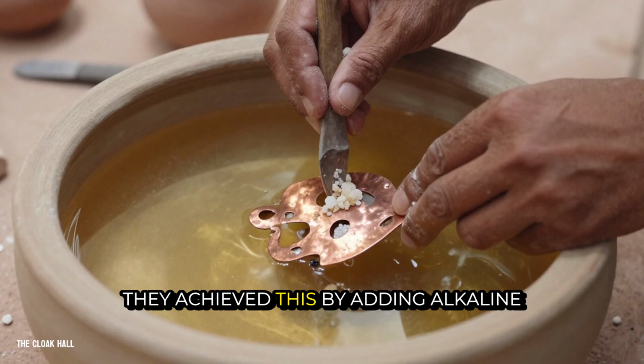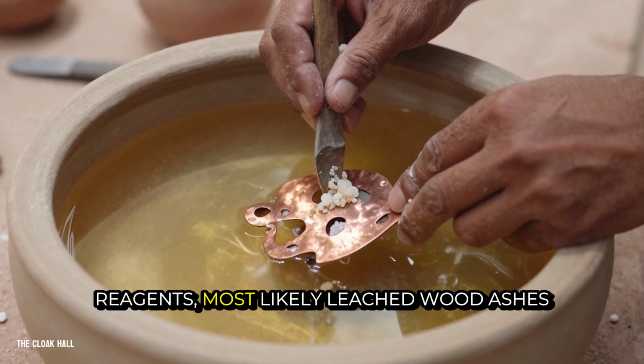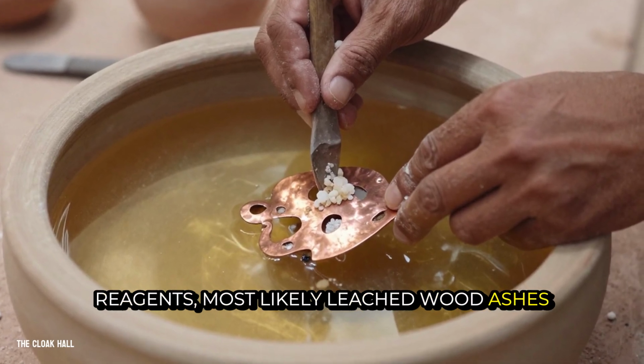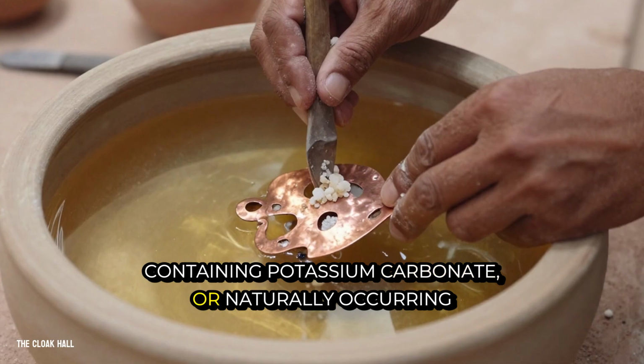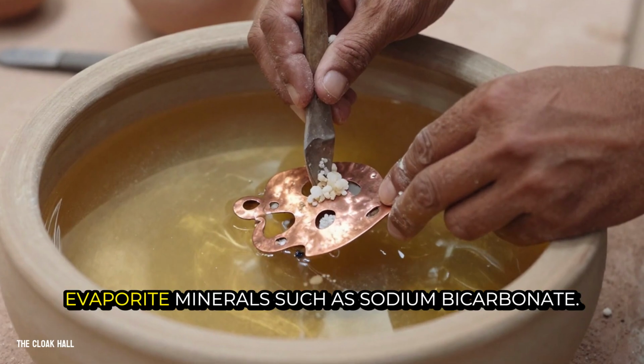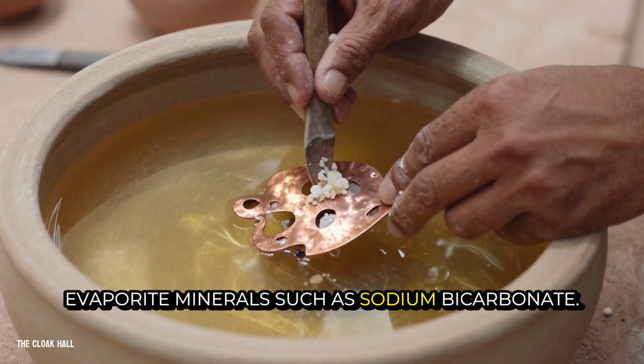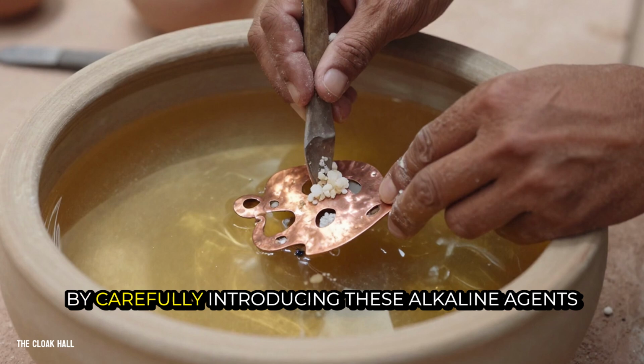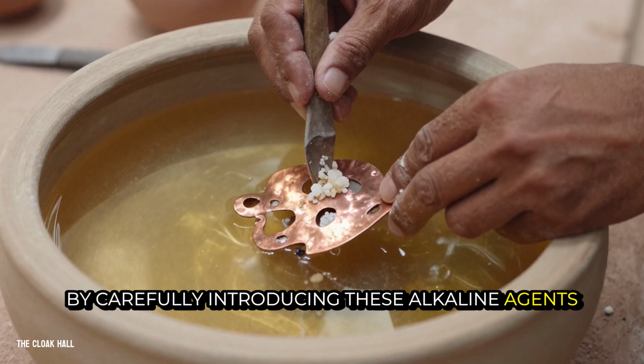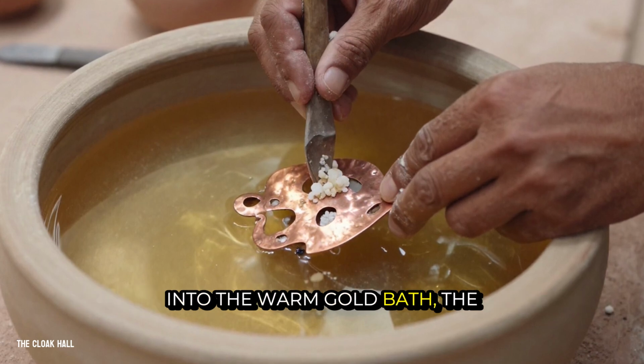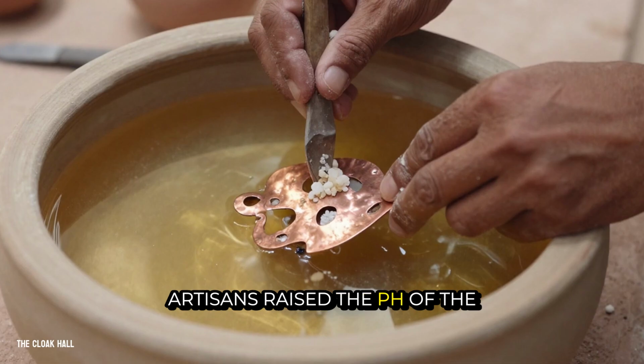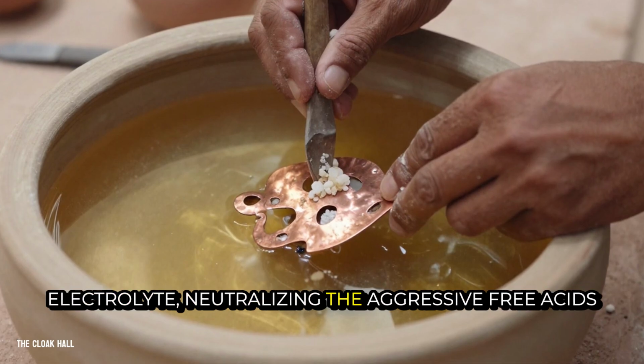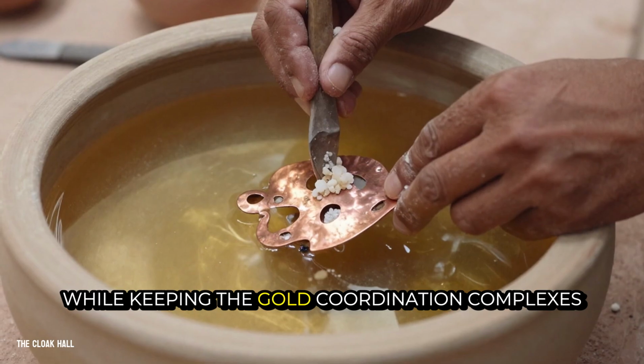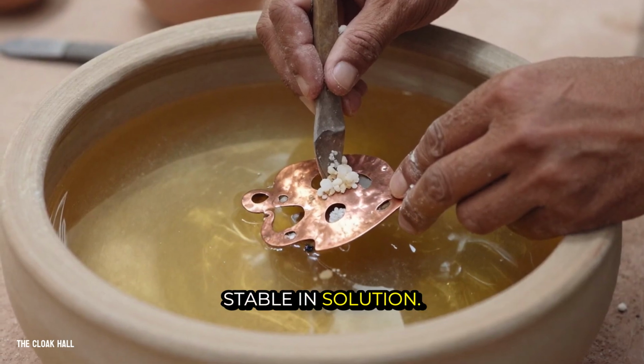They achieved this by adding alkaline reagents, most likely leached wood ashes containing potassium carbonate, or naturally occurring evaporite minerals such as sodium bicarbonate. By carefully introducing these alkaline agents into the warm gold bath, the artisans raised the pH of the electrolyte, neutralizing the aggressive free acids while keeping the gold coordination complexes stable in solution.